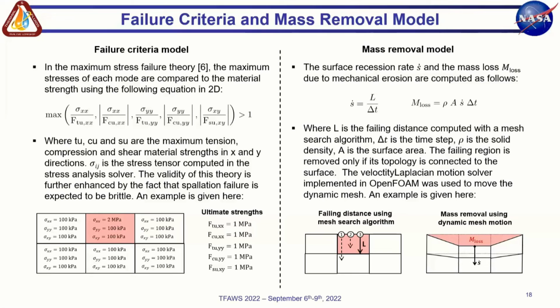Regarding the mass removal model, it follows the two equations shown here. The first one is the surface recession rate, which is the failing distance computed with a mesh search algorithm divided by a time step. And the second one is the mass loss, which also takes into account the solid density and the surface area. The failing region is removed only if its topology is connected to the surface, and if a region fails, the mesh is moved to adapt it to the remaining material.